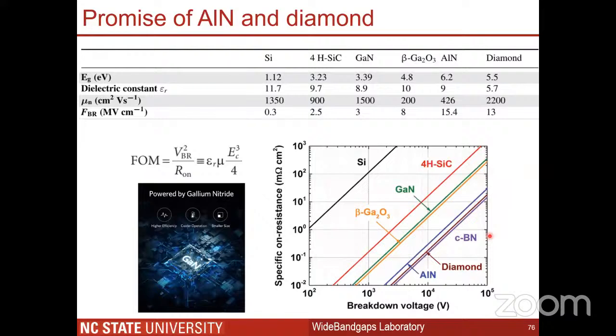So let's look at what the future looks like beyond gallium nitride. So we spoke about how gallium nitride is more efficient than silicon and silicon carbide technologies because of its higher critical field strength and mobility. But now we have development of aluminum nitride that enables a much higher critical field. So you can see that the critical field is 5 times higher than gallium nitride. And in the figure of merit, the field goes as the cube of the electric field, and we can quickly understand how promising aluminum nitride is going to be.